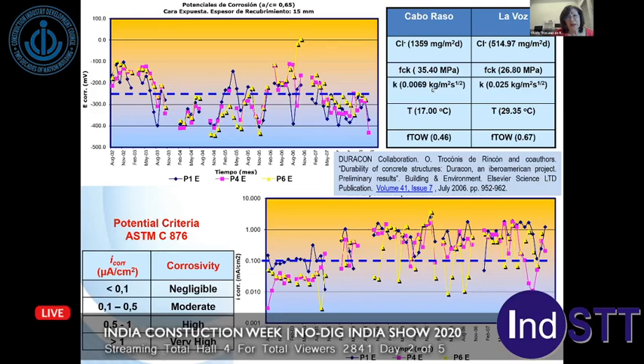Although this location has a concrete mixture similar to Venezuela, as shown in the table, as well as a higher chloride concentration, almost 3 times. Again, the result for the time required for rebar depassivation onset was similar. The figure shows a comparison among the accumulative corrosion rates in the 3 test locations, La Paloma, La Voz, and Cabo Raso. You can observe a higher slope of the curve after the rebar activates for Venezuela, with respect to La Paloma, and then the lower slope is for Cabo Raso.